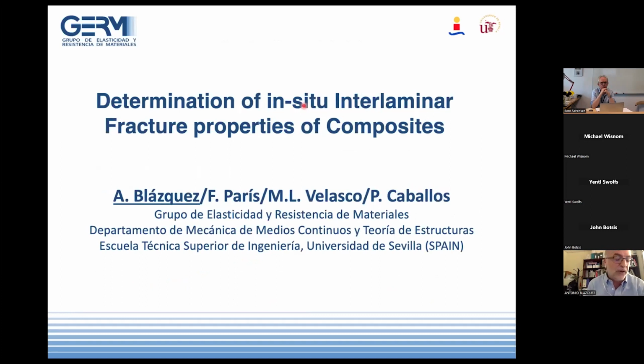Only to finish, I will mention that the results shown in these slides are preliminary. Residual stress is not included, and they are based on what we can see in the lab, that is the configuration of the damage in the surface of the specimen. Nevertheless, the values obtained are much lower than others published by other researchers and also in my group using different approaches. And this opens the discussion about the representativity of the toughness values obtained from tests when using them in the design of an actual structural component. Thank you very much for your attention.